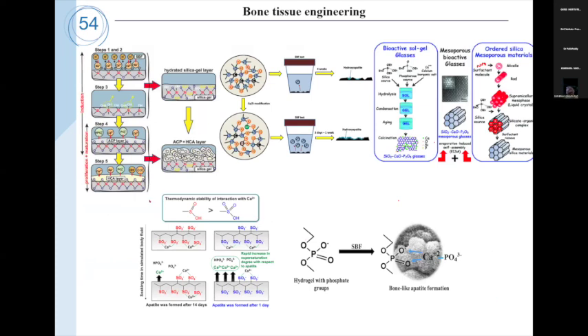So you see here, there are several types of materials that we have to enhance the biomineralization. We can use silica-based materials, silica-based bioactive glass, and other silica materials like mesoporous silica. These materials can accelerate the formation of hydroxyapatite. Moreover, we can also use polymers with some specific functionality, like sulfonic acid groups and phosphate groups. These functional groups can easily interact with the calcium and phosphate ions from the SBF solution, which can accelerate the formation of bone-like apatite via chelation.